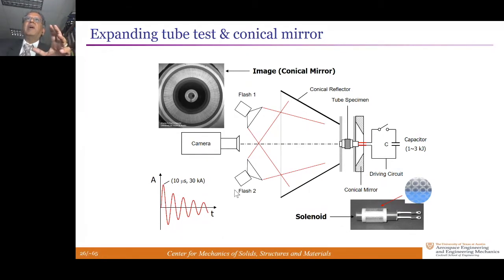The next step in the same experiment is an innovation for looking at cylindrical objects. If you have a tube instead of a ring, it's difficult to diagnose this with the kinds of instrumentation that we have. Typically, we are restricted to watching from one side, a part of the cylinder, and post-mortem examinations. What we decided to do was to take the coil, slip this cylindrical specimen along the coil, build a conical mirror, place the specimen coaxially with the conical mirror so that if you view the camera on the surfaces of the conical mirror, we will see a projection of the entire surface of the cylinder.